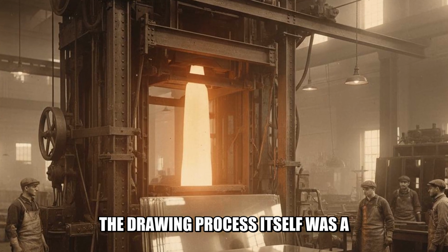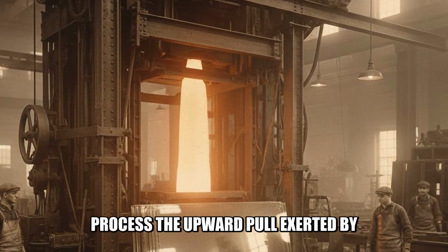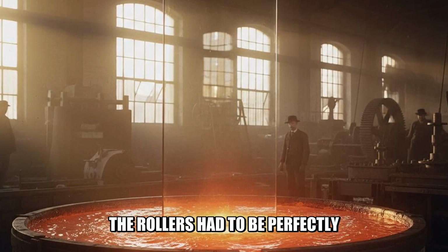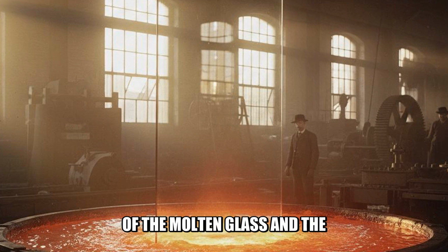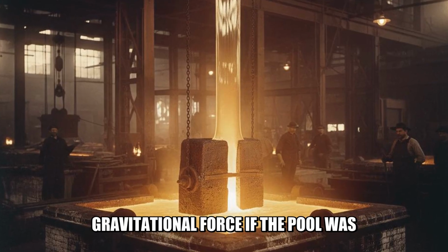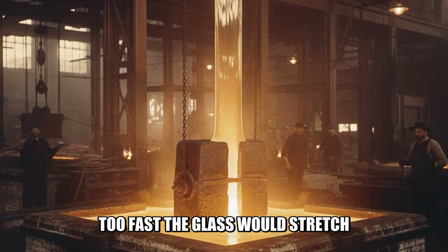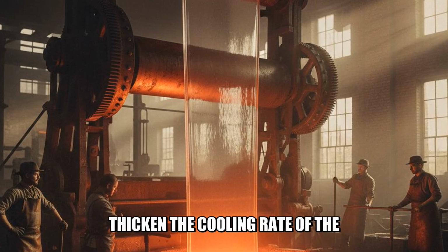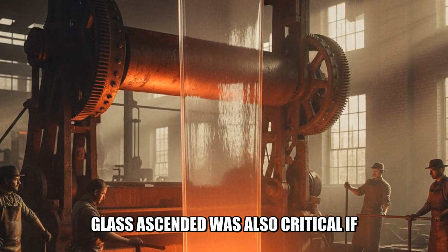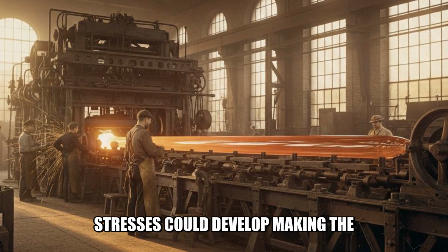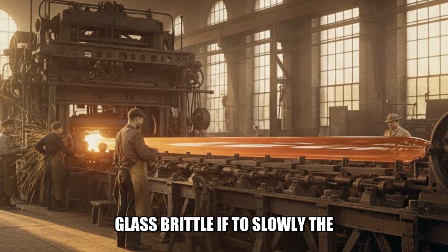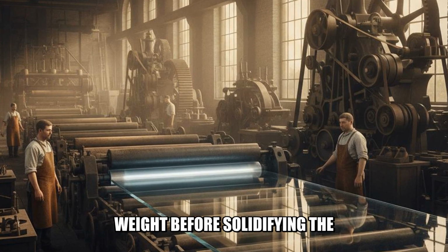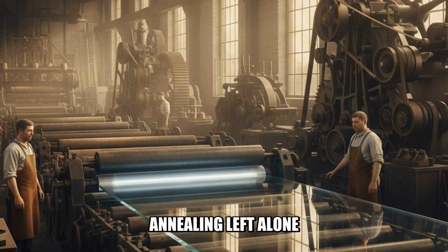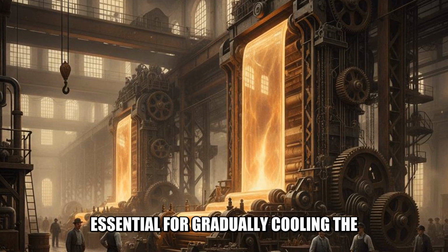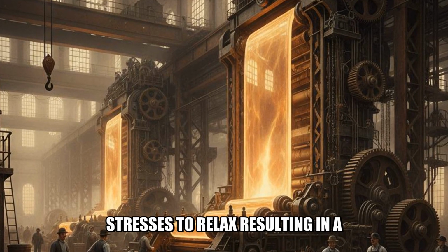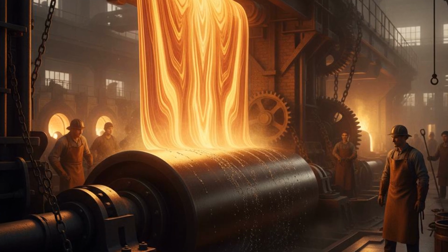The drawing process itself was a dance of forces. In the Fourcault process, the upward pull exerted by the rollers had to be perfectly balanced with the viscous resistance of the molten glass and the gravitational force. If the pull was too fast, the glass would stretch thinner; too slow, and it would thicken. The cooling rate as the glass ascended was also critical. If cooled too quickly, internal stresses could develop, making the glass brittle. If too slowly, the glass might deform under its own weight before solidifying. The annealing lehr, a long, temperature-controlled tunnel, was essential for gradually cooling the glass, allowing these internal stresses to relax, resulting in a stronger, more stable product.